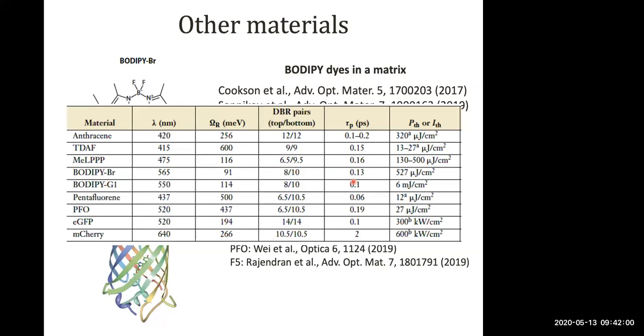And so we have this nice summary table from the paper highlighting the properties of these different systems. And the lowest thresholds are observed in these fluorene systems. So TDAF, pentafluorene, and PFO show polariton lasing thresholds on the order of about 10 to 20 microjoules per square centimeter. And both protein systems have the advantage of showing very stable condensate emission under nanosecond pulsing, which is interesting for several applications.